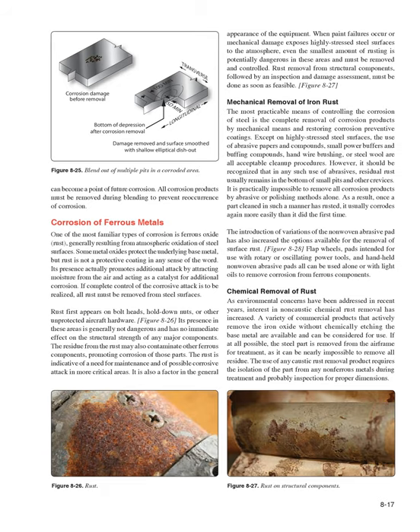However, it should be recognized that in any such use of abrasives, residual rust usually remains in the bottom of small pits and other crevices. It is practically impossible to remove all corrosion products by abrasive or polishing methods alone. As a result, once a part cleaned in such a manner has rusted, it usually corrodes again more easily than it did the first time.